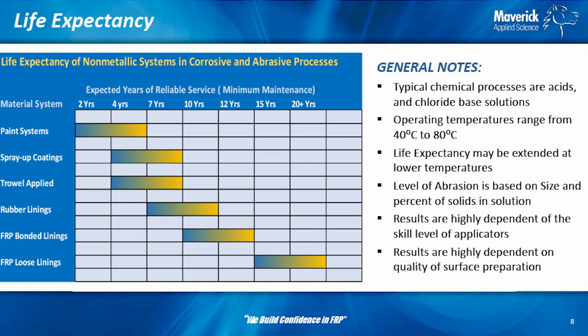And then we look at some spray up coatings that may be epoxy coatings. There are spray up systems for FRP as well. Those are much the same application. Generally, they're a little bit more robust, a little bit thicker. Sometimes they might have 10% of some sort of reinforcement, like glass beads or something else. Generally, we see a little bit better out of that. I would say typically, probably 7, 8 years is what we typically see, maybe up to